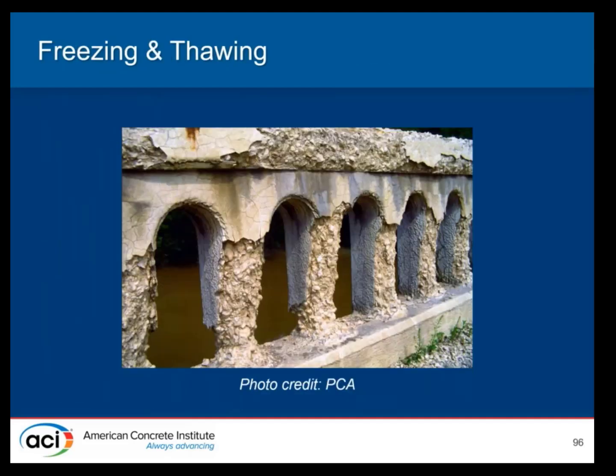Okay. Freeze-thaw damage. Deterioration of concrete occurs once the concrete becomes critically saturated, which is approximately 91% of its pores filled with water. When water freezes to ice, it occupies 9% more volume than that of water. That's why ice floats. If there's no space for that volume expansion in a porous material, the water inside the concrete will freeze, causing distress in the concrete. And you can get this freeze-thaw damage. You get this typical scaling pattern where the paste is actually popping off and the aggregate remains intact.